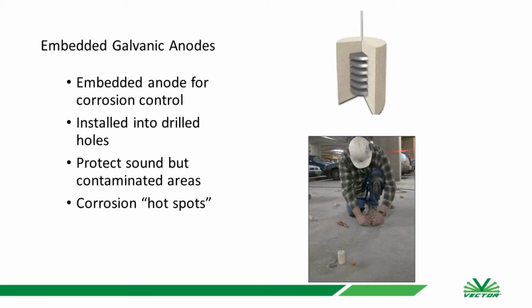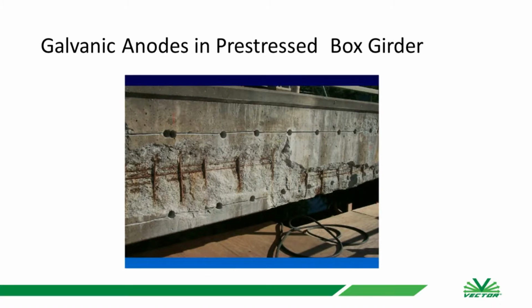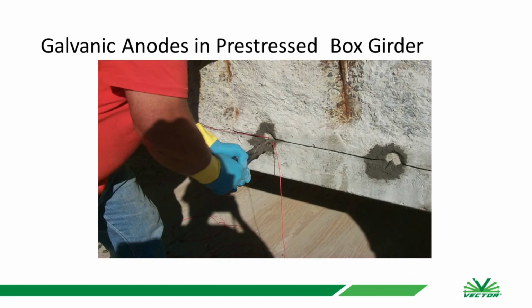So rather than having to open up an entire patch and get rid of all this concrete, literally what they're going to do is core into specific areas where they want to target corrosion protection and run them in a series and attach them that way. You can see here are the drilled holes where they put in these type of anodes for the protection of the steel, and then they're just going to do a saw cut in between them. Between that saw cut, they'll lay wire and attach each one of these anodes individually.